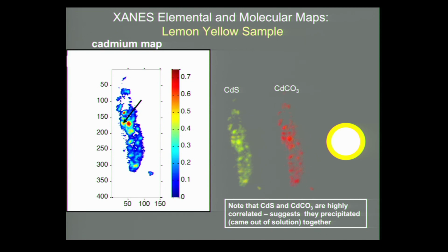And what we're looking at here is elemental and molecular maps for this lemon yellow sample. All of the hot spots in this map are the different cadmium-containing pigment particles. And the real exciting information is that if we map out cadmium sulfide and cadmium carbonate, you can see that they're highly correlated. And this suggests that these materials were precipitated or they came out of solution together.